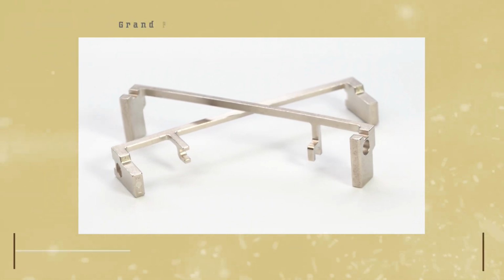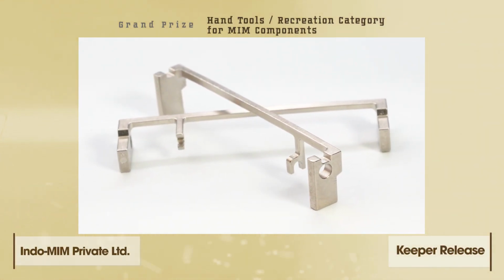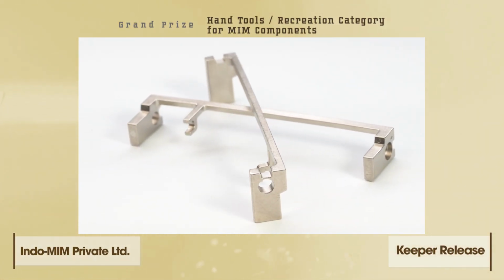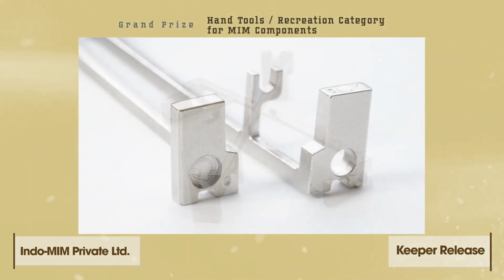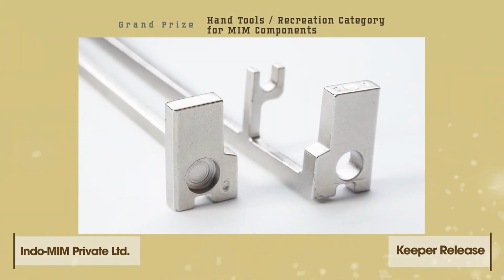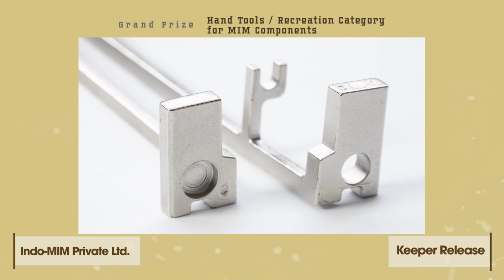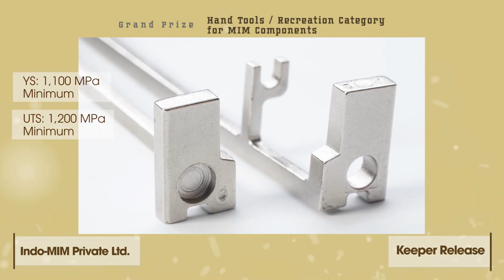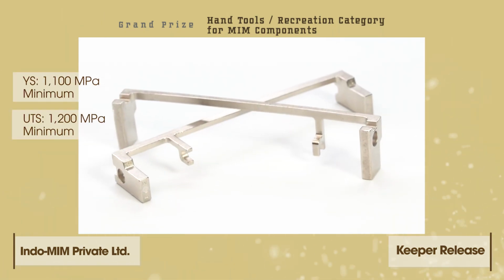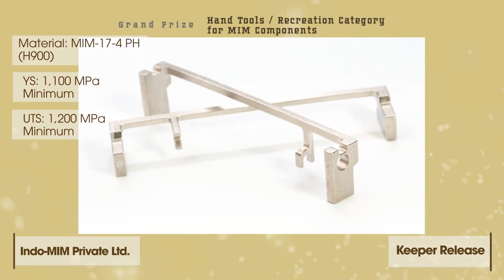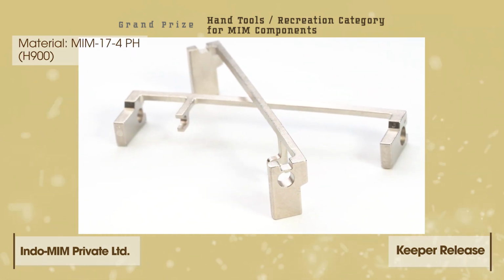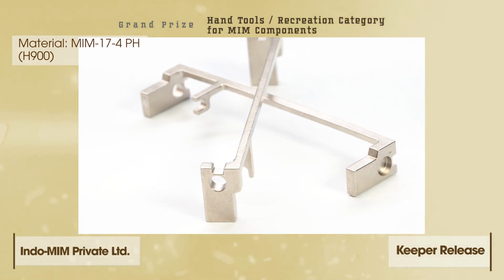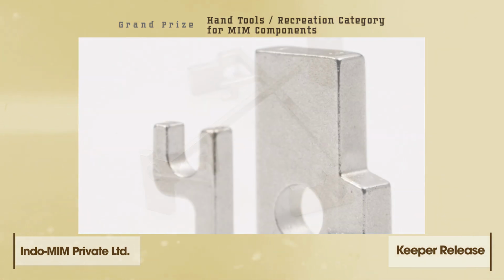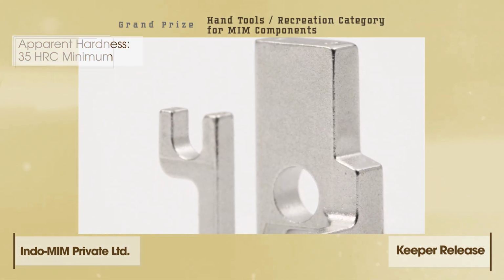Indomim Private Limited received a grand prize in the hand tools recreation category for MIM components for a keeper release. Door locks must sustain frictional force and wear and tear during operation. MIM was selected for this keeper release used in a sub-assembly for safety door locks. The keeper release is made using MIM 17-4PH stainless steel, and the parts are given an H900 temper to achieve an ultimate tensile strength of 1200 megapascal and a minimum apparent hardness of 35 HRC.